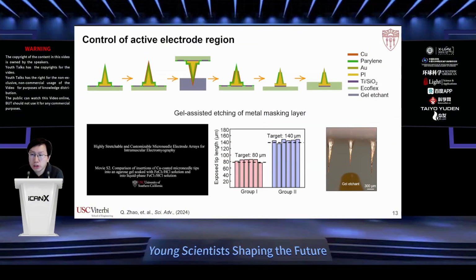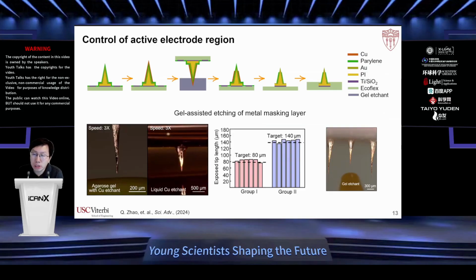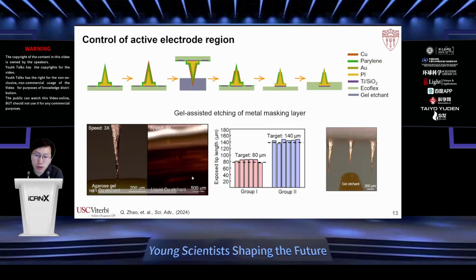And another challenge we overcame was how to make sure that we only expose the tip of the conductive microneedle. The key idea is that we use parylene for encapsulation, but then we etch the parylene at the tip using a copper hard mask. Eventually, we need to etch the copper at the tip. And we found that if we use the liquid copper etchant, it's going to spread and prevent us from only etching the tip. So we developed an agar gel-based etching system, basically immersing agar gel into copper etchant,